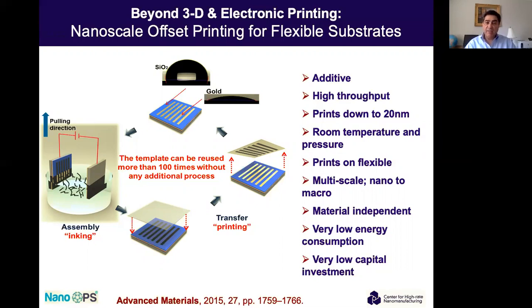So it's additive, it's high throughput. You can do a wafer, the inking of the template takes a minute, the transfer takes a minute, and you can align between layers also. You can print down to 20 nanometers, at room temperature and pressure. Multi-scale, you can have nano on micro and macro. It's material independent. We've tried a variety of materials, very low energy consumption, and you can see it's one tool basically. Very low capital investment.